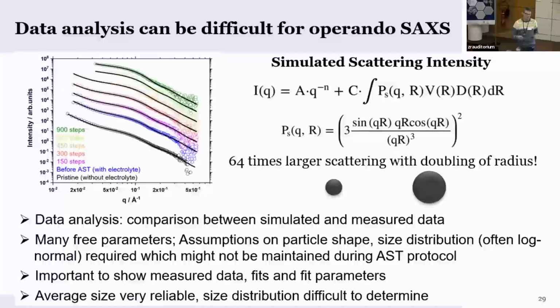So in typical data analysis software like SASView, you assume a size distribution like a log normal distribution. That is typically what you get after synthesis. And then you can have one size or multiple sizes. You also have to assume a particle shape. And then you basically have a simulated spectrum you compare to your measured scattering data.